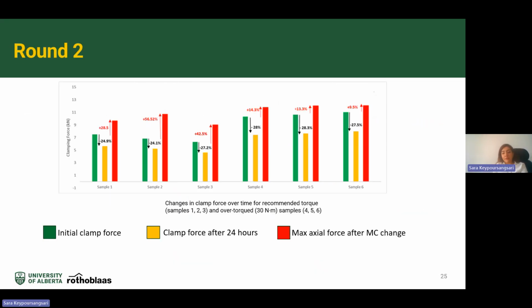Here you can see the summary of the results and the effect of the relaxation after 24 hours, and also the final load, which was measured by the load cells. This figure shows the importance of the installation torque, because in samples 4, 5, and 6, we applied the torque of about 30 Newton meter. The level of the moisture was the same, but in samples 4, 5, and 6, the over-torque was higher than in these samples. You can see the final load in this group B was higher.